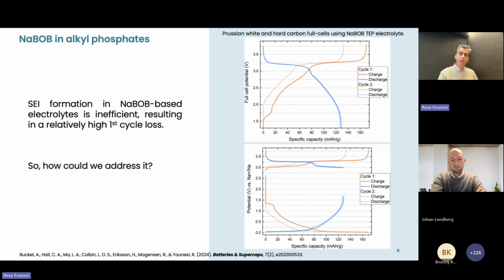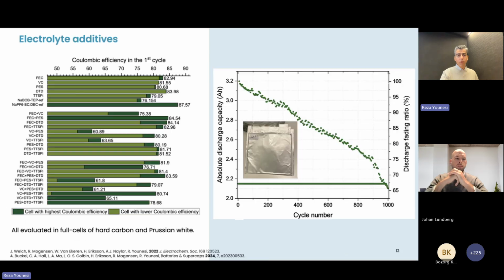And then what you see in the figure top right, there is a small shoulder around 1.7 volts. That is where sodium BOB is decomposed. And the decomposition products are very soluble in the electrolyte, which means that there is no passive layer formed, no efficient SEI. So what we could do here is play with the formation protocol to optimize the first cycle, as we have shown in one of our studies that you see down in the note. The other possibility is to optimize the electrolyte by different additives.